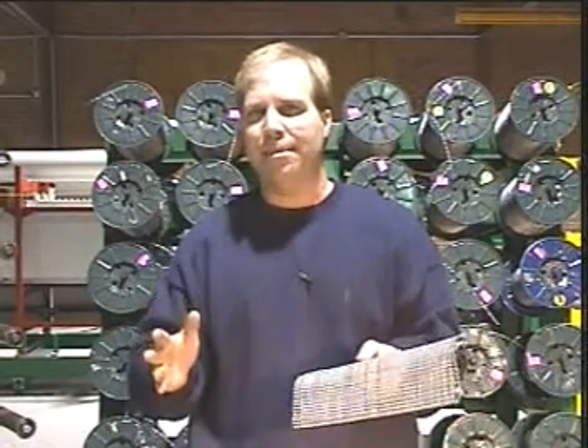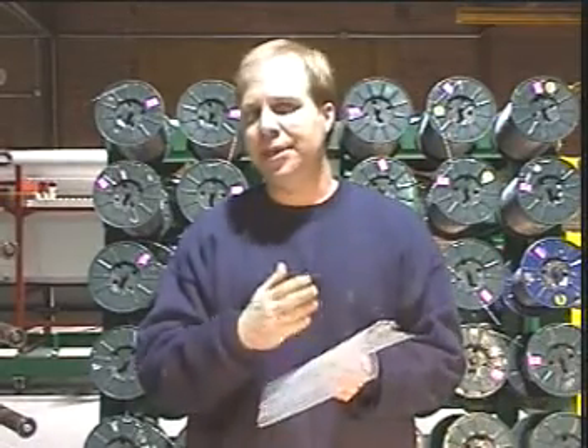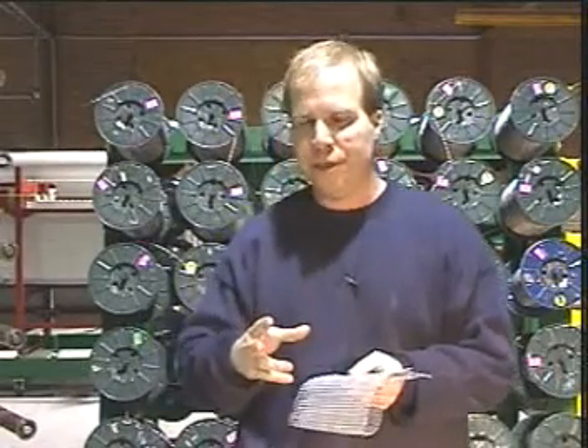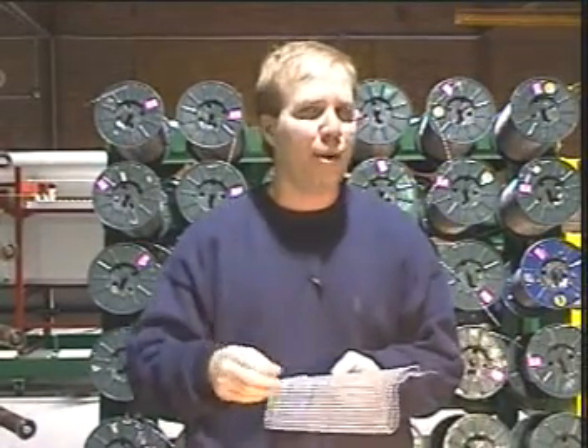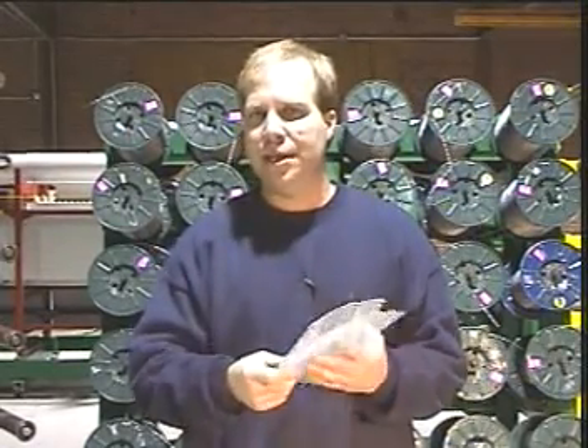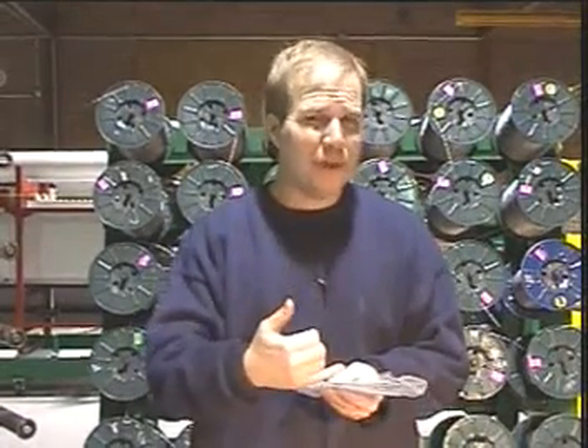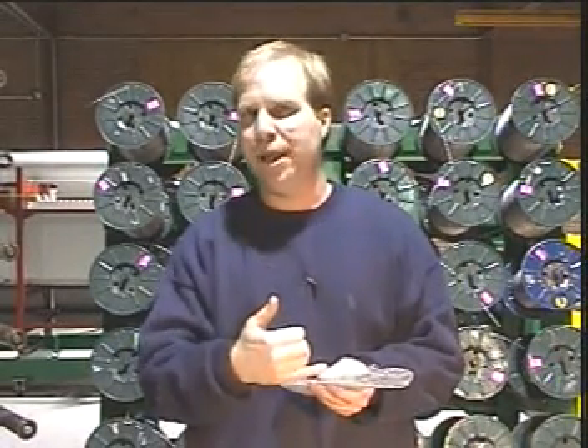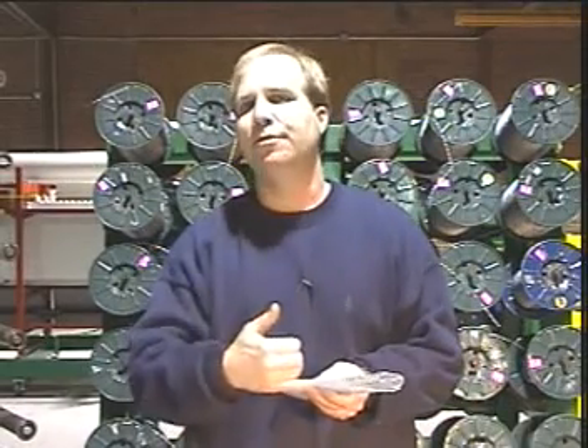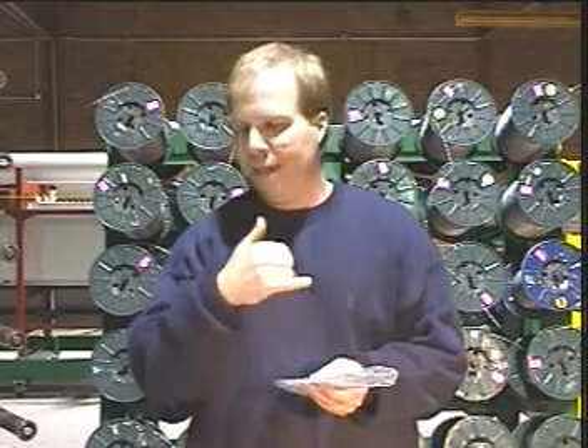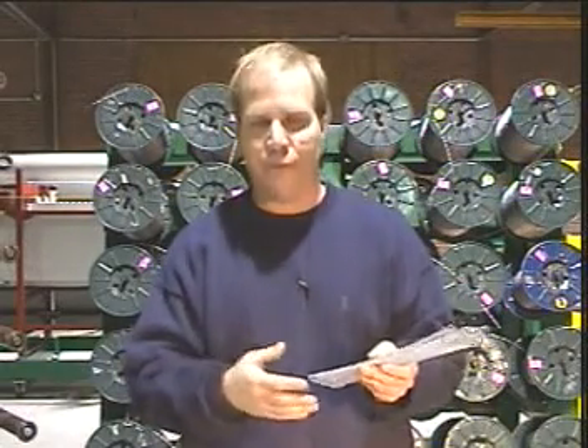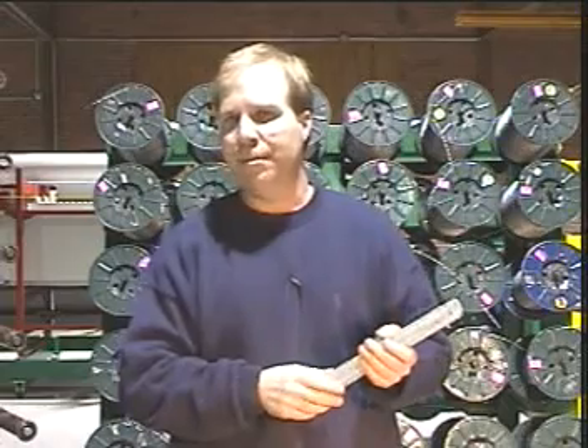So when you add all that up, a lot of these advantages end up being squared or cubed in terms of mold turnover. What we're finding is customers using Hardwire can easily turn large parts in a molded system over in a single shift, whereas in glass or carbon, just the long layup time, we're talking about hours for infusion for very large wind blade parts, and then of course hours longer for the peak exotherm and demold time. Those kinds of dramatic time increases can save our fabricators, the Hardwire fabricators, tons of time and money.